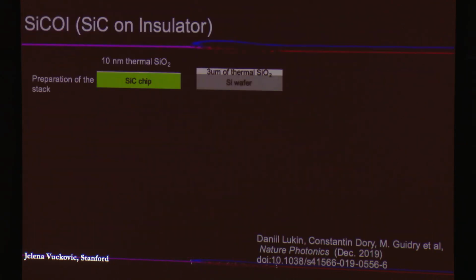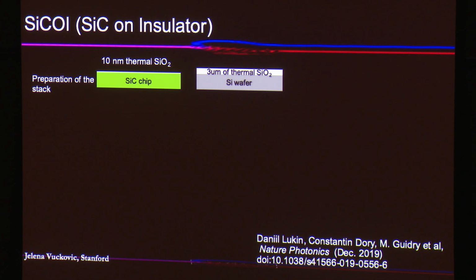And we spent a few years trying to make silicon carbide on insulator. We tried smart cut, and we succeeded. We transferred silicon carbide to insulator. Smart cut is ion bombardment, liftoff, bonding. That's what people actually do for silicon. But that damaged the material, because you bombard it with ions and it introduces unintentional defects. And we want to have only intentional defects, right? Because we are bombarding afterwards to introduce vacancies.